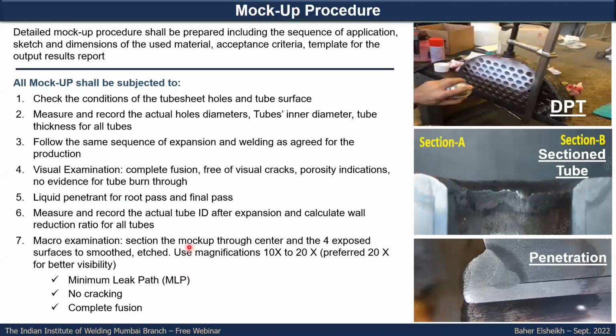This is for sure for the expansion cases. And then do the macro examination. And while doing the macro examination, ASME here is recommending magnification 10x to 20x, but actually it is highly preferred to be 20x or maybe even 25x to have a good representation of any lack of fusion, porosity or lack of penetration. The quality of the weld joint is highly crucial for the long lasting life of the heat exchanger. And then you need to calculate and see the minimum leak path, and you need to make sure that there is no evidence of cracking and that it has complete fusion.